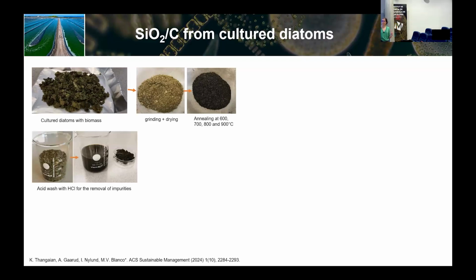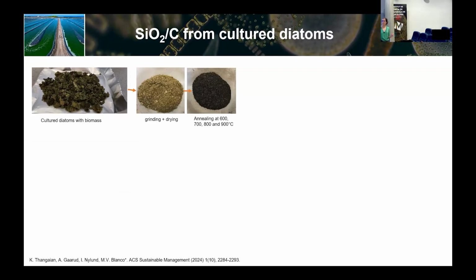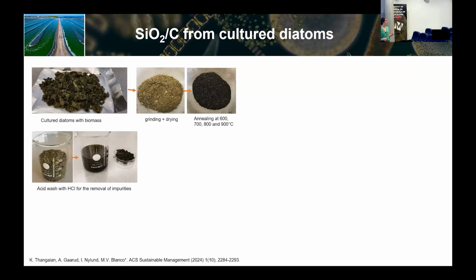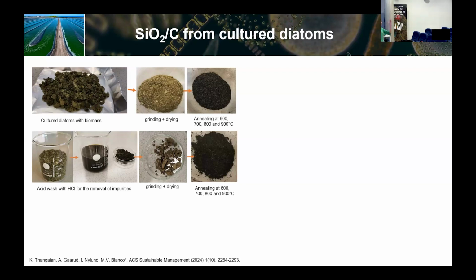And then we see the same thing, but doing some acid wash first, just to get rid of impurities that come with organic matter. And then we did the same thing: grinding and drying, and then annealing. And then we compare the results of how these materials were coated.